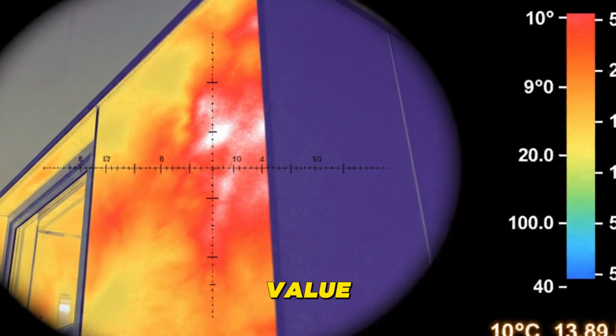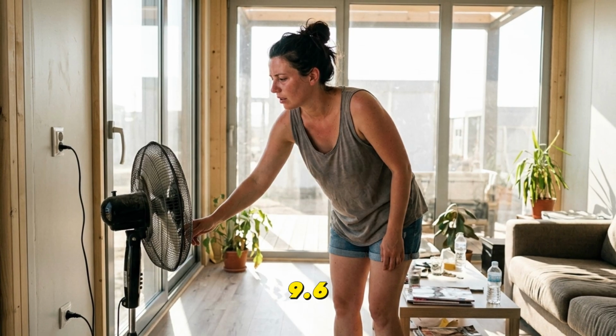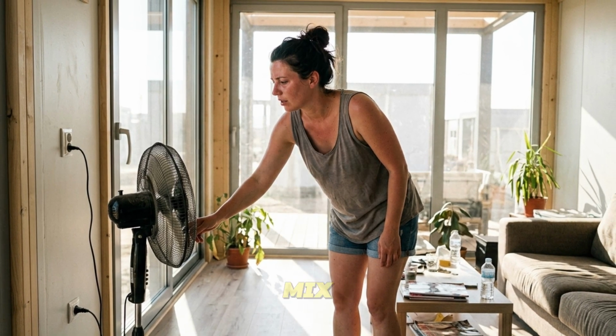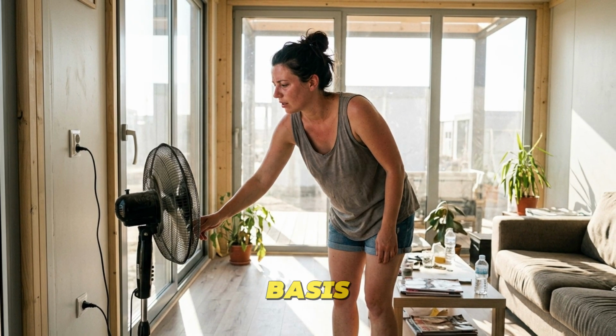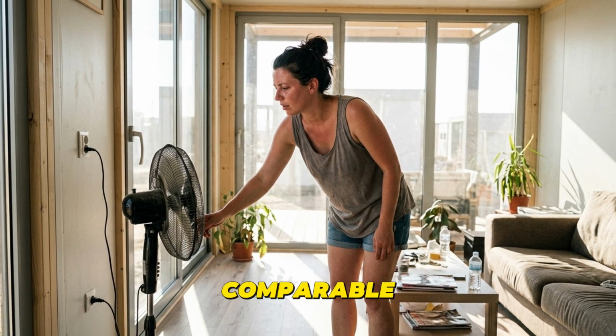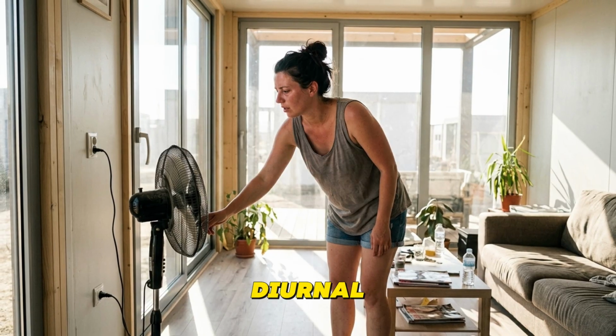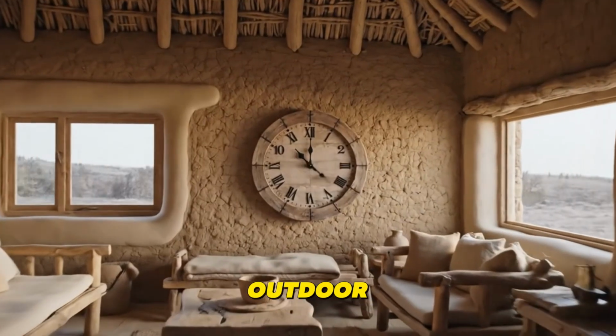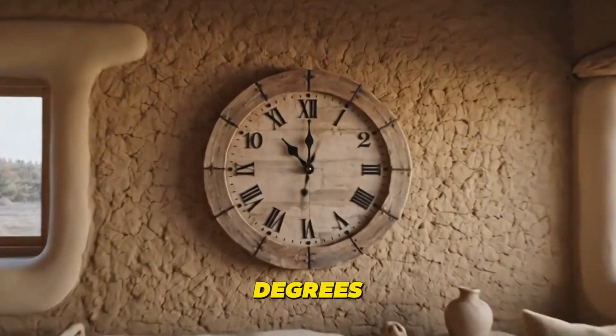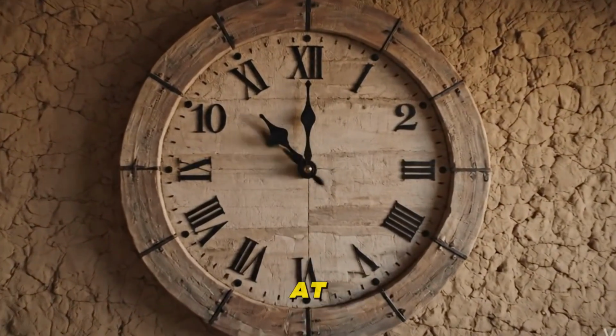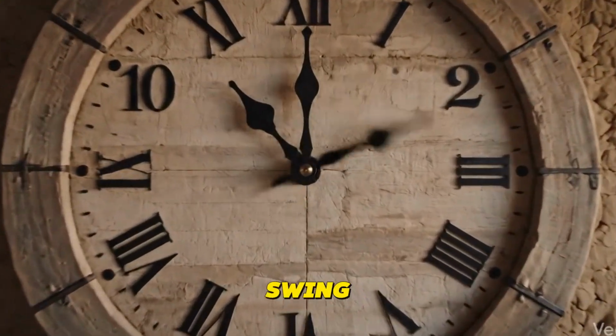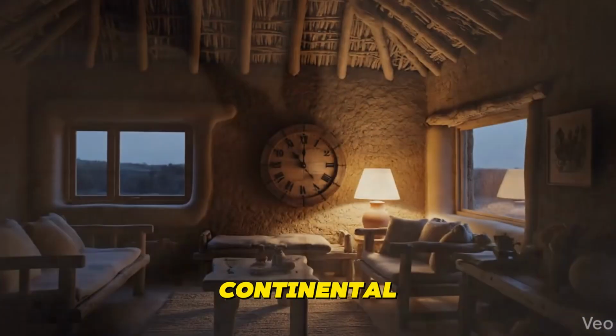This is a typical wall specification for a residential building in a moderate climate zone in the United States. A 24-inch cob wall has a steady-state R-value of approximately R9.6 to R12, depending on mix density. On a steady-state basis, these walls are roughly comparable. Now apply a diurnal temperature swing, a realistic outdoor temperature that goes from 55 degrees at night to 85 degrees at midday. A 30-degree swing typical of summer in a continental climate.